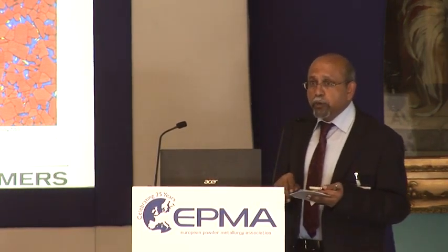What is rather new is that we can not only calculate the phase diagrams, but now the latest is that we can start calculating the interfacial phase diagrams because we do not have equilibrium conditions during sintering. We always think we have equilibrium conditions during sintering and after cooling, but in reality, it's not in equilibrium. And what happens at the interface between the carbide-carbide or the carbide binder is the most important thing for all mechanical properties for your material, as well as for the chemical properties like corrosion resistance. So just about 3 or 4 months ago, I had the opportunity to listen to a talk. I didn't understand everything, so I will not go into detail.